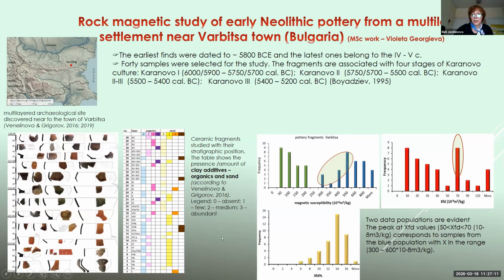And we also carried out magnetic measurements on the collection. You can see the magnetic susceptibility data. Generally, we obtained 2 groups of samples, one with relatively low susceptibility and the other with higher magnetic susceptibility. But it was found that the samples with susceptibility values in the intermediate range show very high frequency dependent susceptibility, although the percentage frequency dependence showed only a single peak in the distribution of the data.